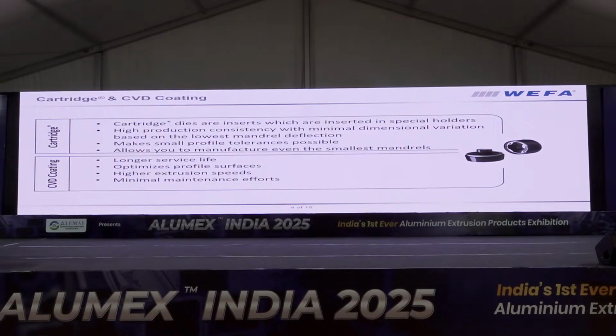Minimum maintenance effort: I was explaining that if you have 5 to 6 times renitriding, the die needs to come out of the press and be put into caustic soda. We can eliminate this. The dies can be used without any caustic treatment, so you can even leave aluminum in the die and run and run and run. Last but not least, with CVD, the smallest tolerances are possible. Nitriding comes from two sides into a mandrel, and with only a 10 micron thick coating, that can be eliminated.